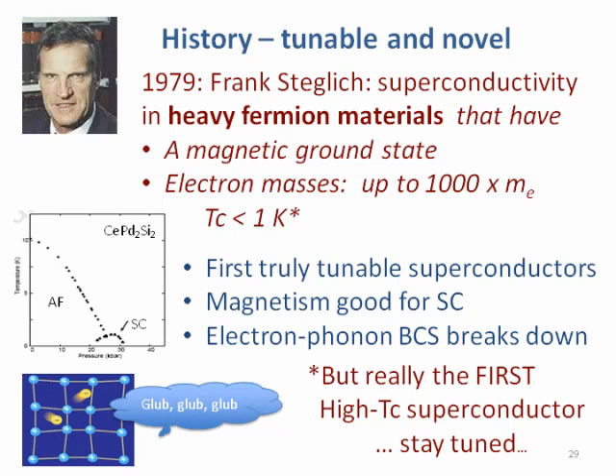And this is the first time we realized that magnetism is actually good for superconductivity, because all of those non-conventional superconductors have a magnetic portion, have some magnetism in the phase diagram. And this is when we started to realize that the electron-phonon mechanism, or the electron-lattice mechanism, the BCS theory of superconductivity, probably didn't hold in these materials. And that's most of the superconductors.